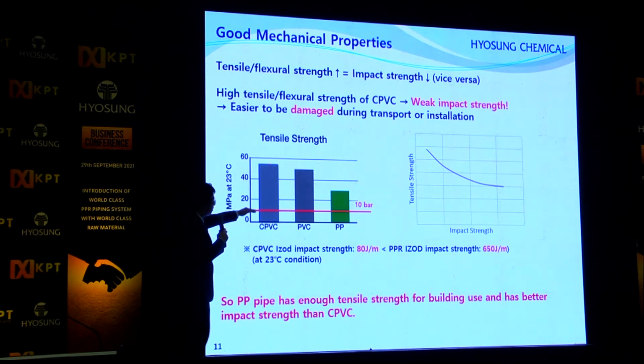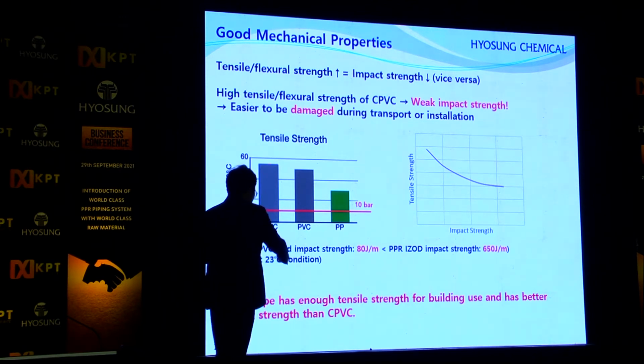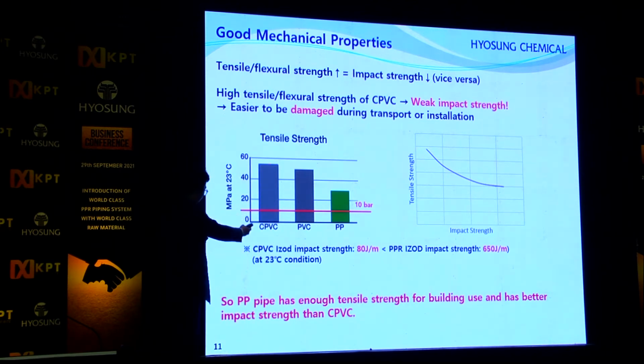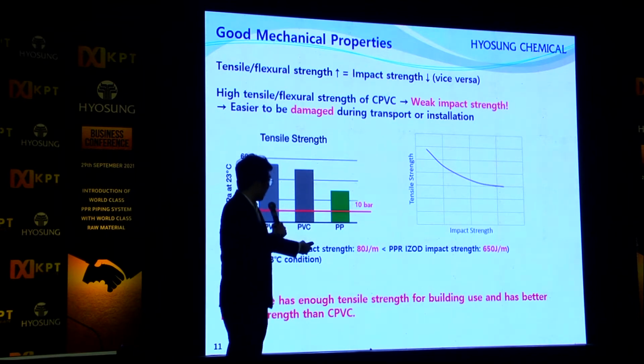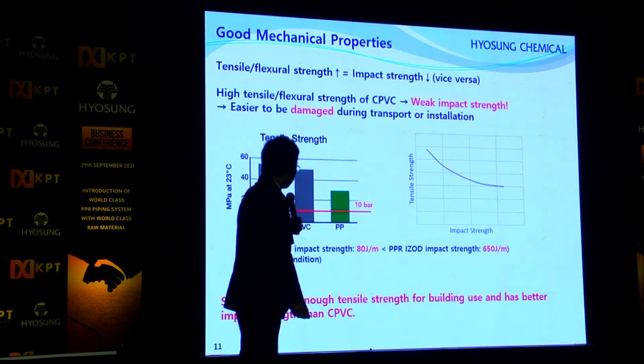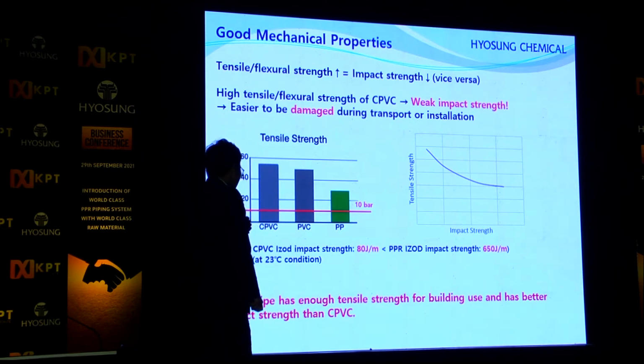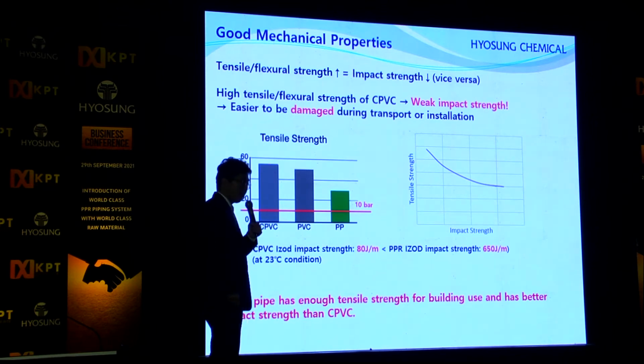And this line is 10 bar, the same as the line I showed you previously. Still, PP tensile strength has enough strength for usage. But when we see the Izod impact strength, CPVC has only 80 joule per meter, but PPR has 650 joule per meter. So we have more than 8 times higher impact strength.